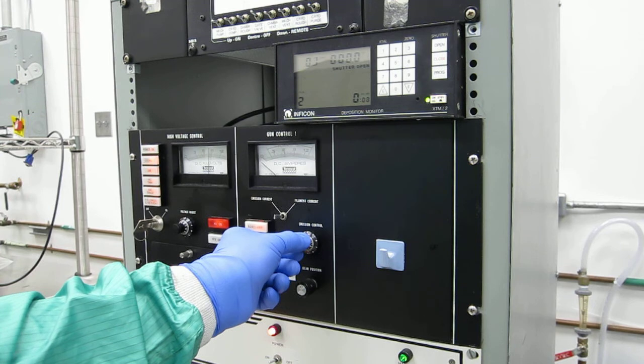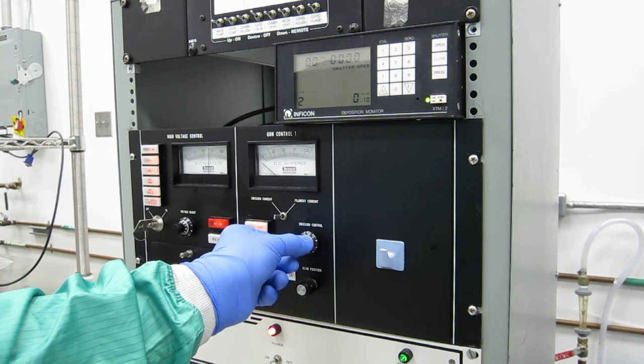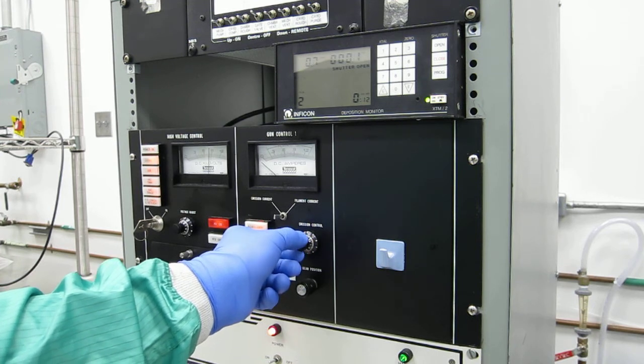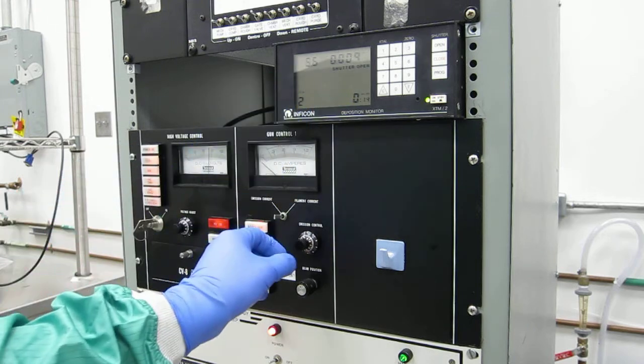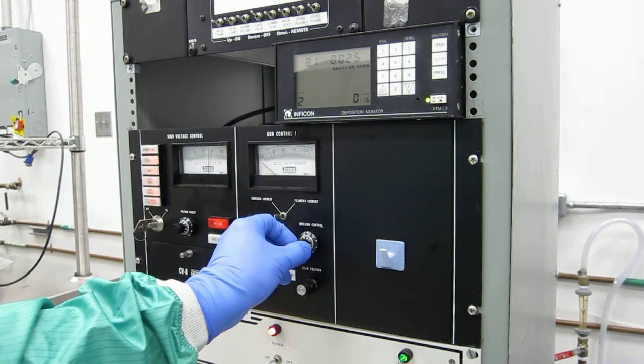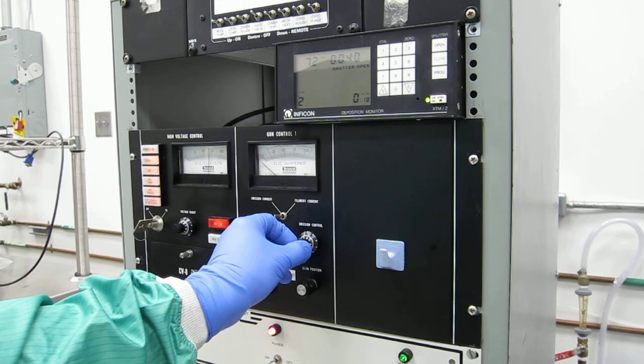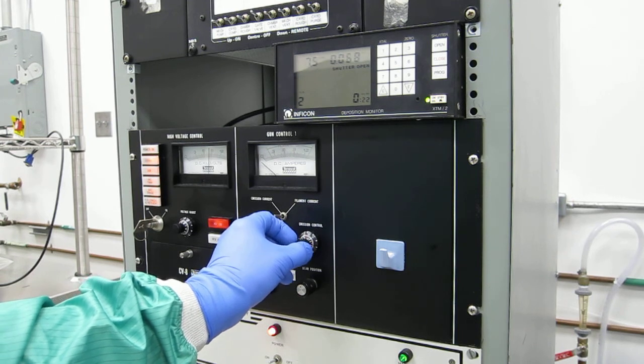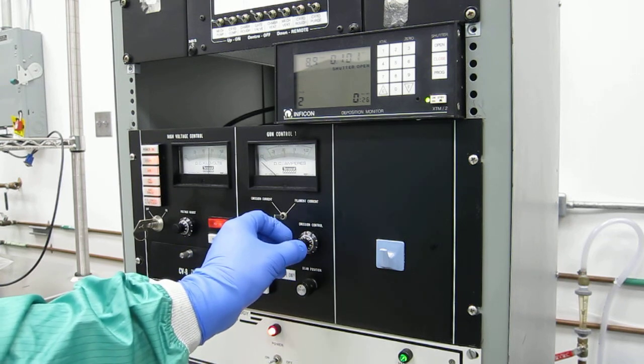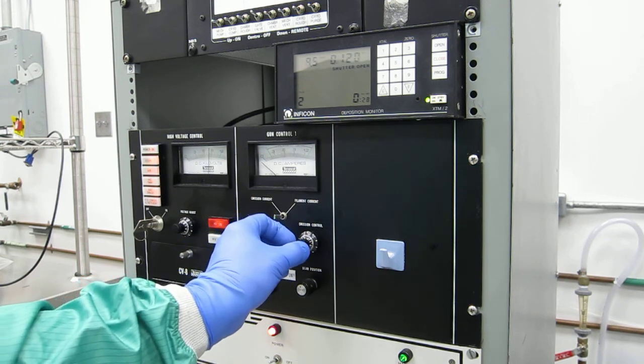Now simply increase the heat of the source until we get the desired rate. If the rate's too high, turn it down. If the rate's too low, turn it up. Our target deposition in this case is 900 angstroms.